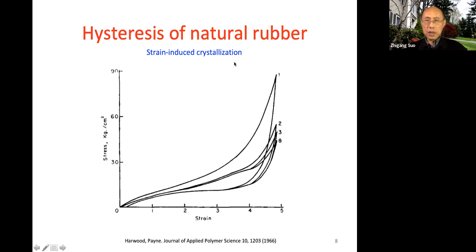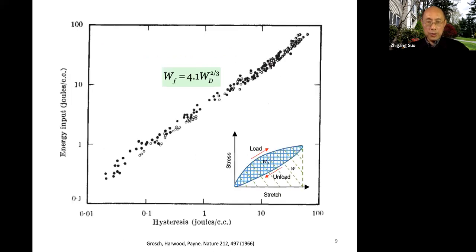That's not true. It was discovered about 100 years ago that natural rubber has the ability to crystallize under stress. When you stretch rubber, the rubber chains become straight and they crystallize. When you release the stretch, the crystals melt. So it actually has a hysteresis. It was known for nearly 100 years. The same group of people even related this hysteresis energy, the blue shaded area, to the total work you put in. That is, you load, unload, and when you fracture, you release the entire energy under the load curve.